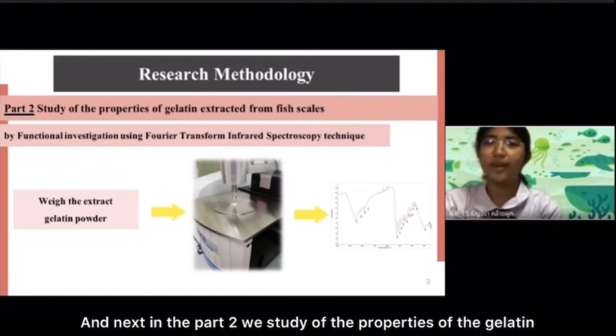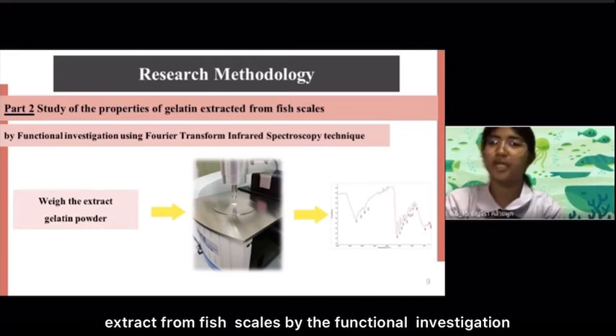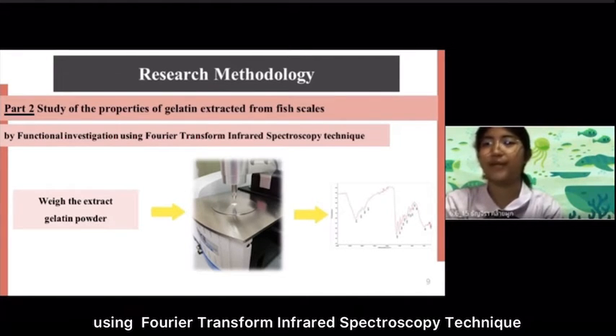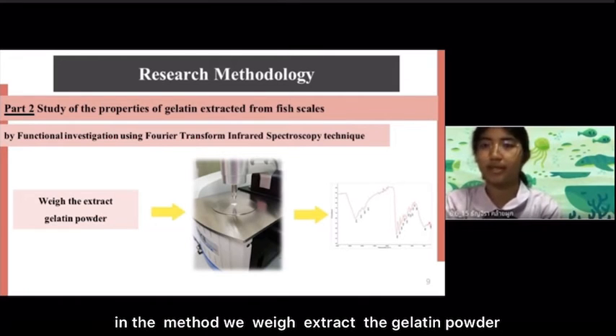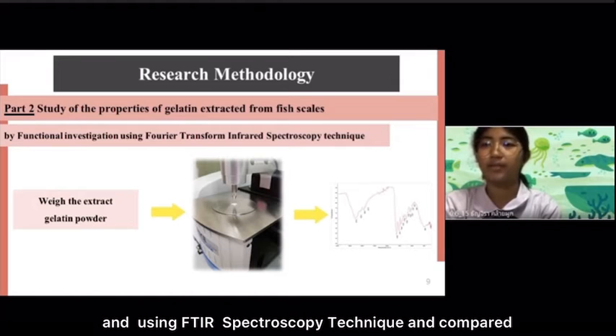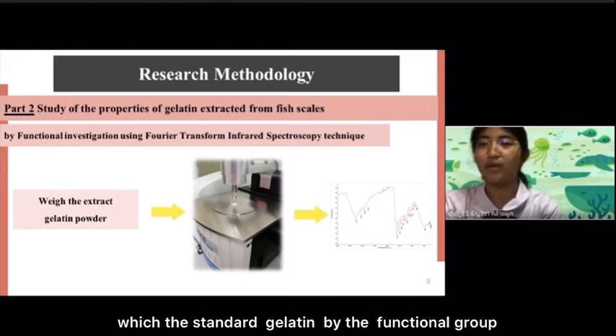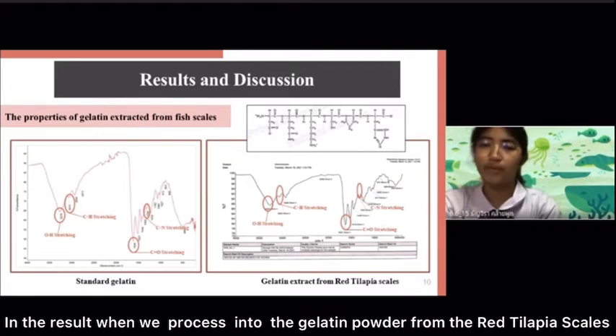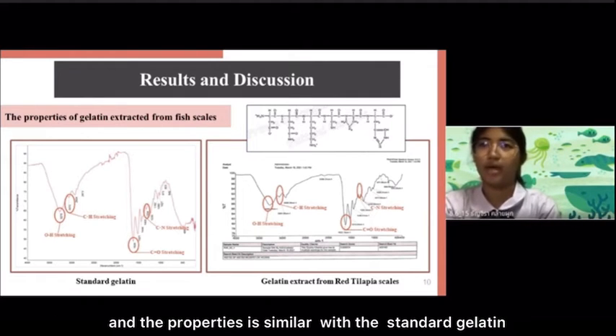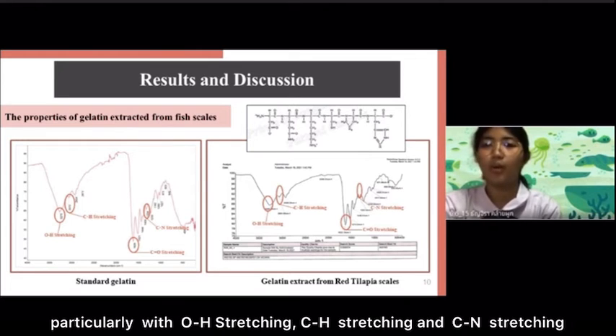And next, in part 2, we study the properties of gelatin extracted from fish scale by functional group investigation using Fourier transform infrared spectroscopy. In the method, we weigh the extracted gelatin powder, use the FTIR spectroscopy technique, and compare with the standard gelatin by functional group. In the result, when we process the Red Tilapia scale into gelatin powder, the properties are similar to the standard gelatin, particularly with OH stretching, C-H stretching, and CN stretching.